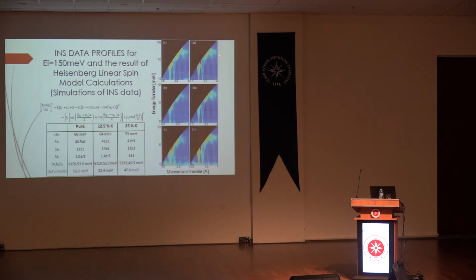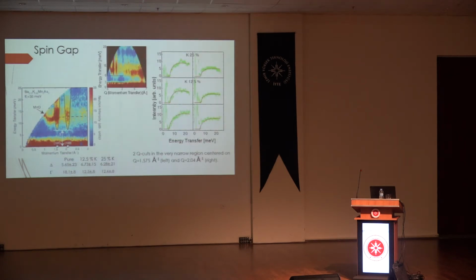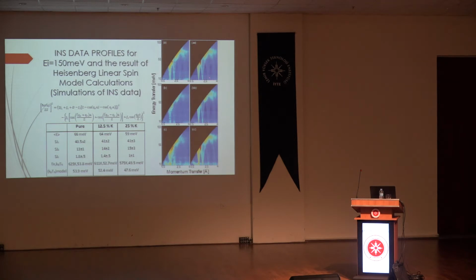As you see, it looks very good compared to the data. And you may see some background changes there too, and there as well. That is pure, 12.5%, 25% potassium. So we realize altogether that not only having the correct intensity for the magnetic scattering, but also, maybe more, having a perfect definition of background is crucial for the goodness of the fit. So what we do is basically define the background. I'm going to go to the background definition on the coming slides in a minute.